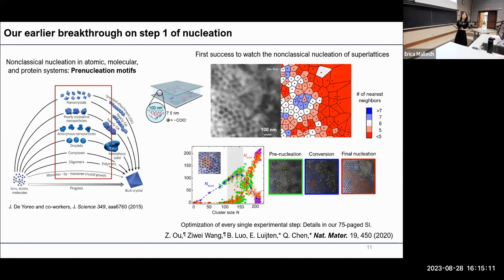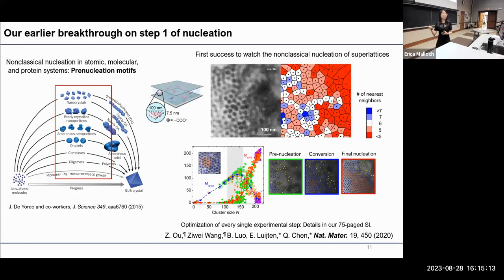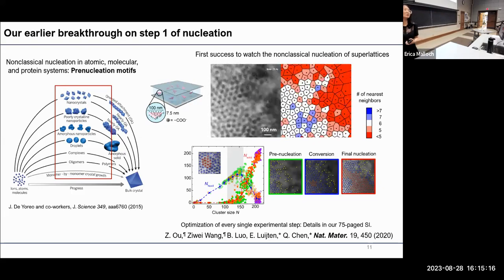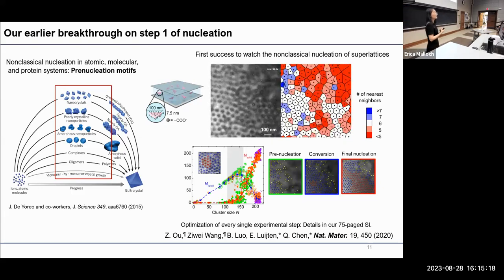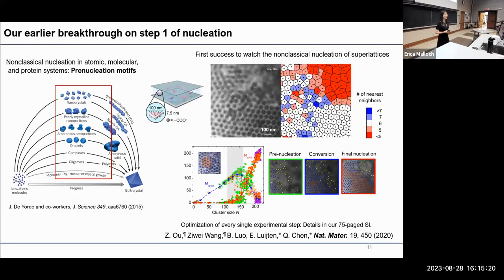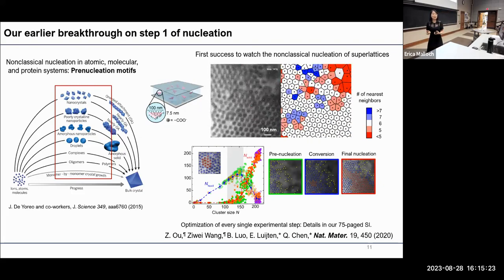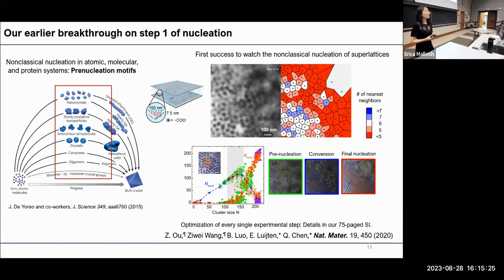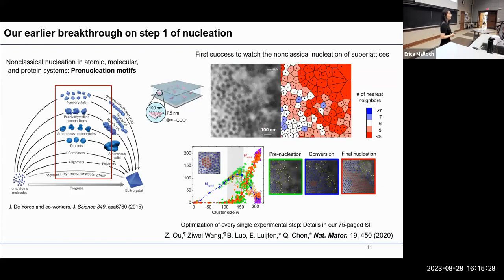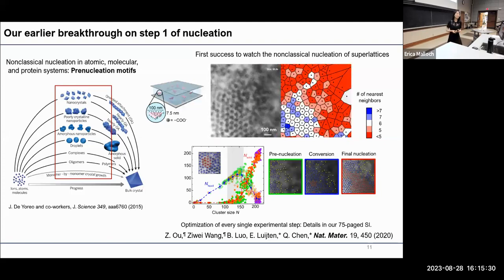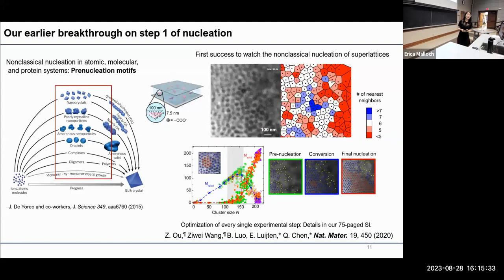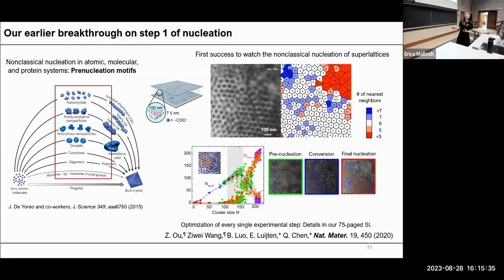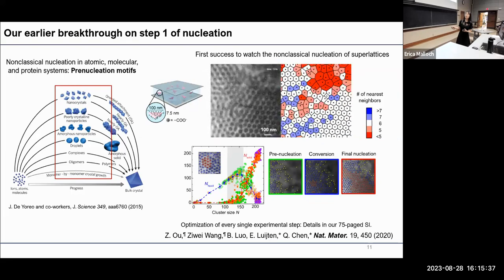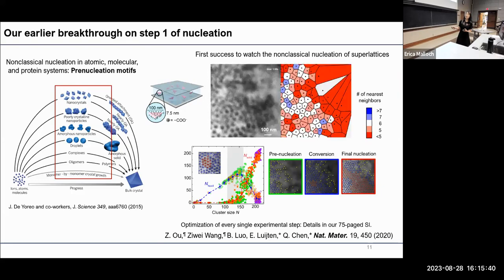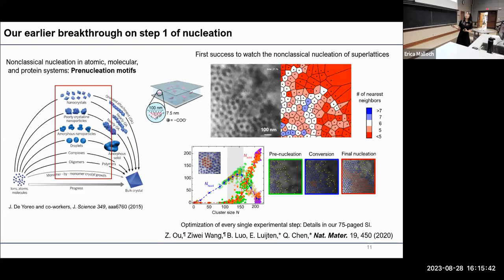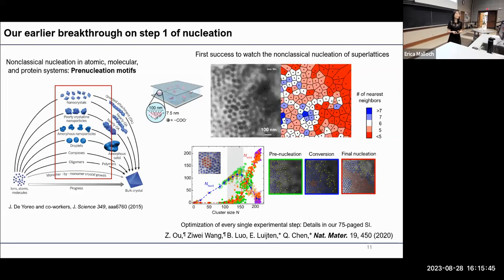In a TEM movie, the black things are our nanoparticles. They're moving very vividly because they're in solution. They have Brownian motion, and they're interacting with each other to form an ordered lattice. We can also do single particle tracking to chart a crystallization coordinate, from which we can identify a non-classical nucleation pathway. Non-classical nucleation means that instead of following the classical pathway to directly form a crystal from individual building blocks, you need to go through a collection of pre-nucleation motifs.